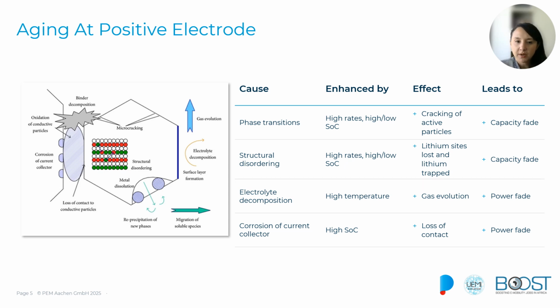Now let's see what happens in the positive electrode. In the positive electrode, or the cathode, we will experience aging mostly due to structural changes and the chemical reactions that occur during charge and discharge. Over time, high charge rates and extreme operating conditions, like high or low temperatures, will lead to phase transitions. These phase transitions within the cathode materials will cause cracks and loss of active materials, which at the end will result in a reduction in the ability of the cathode to effectively store and release lithium ions, leading to the gradual loss of battery capacity.